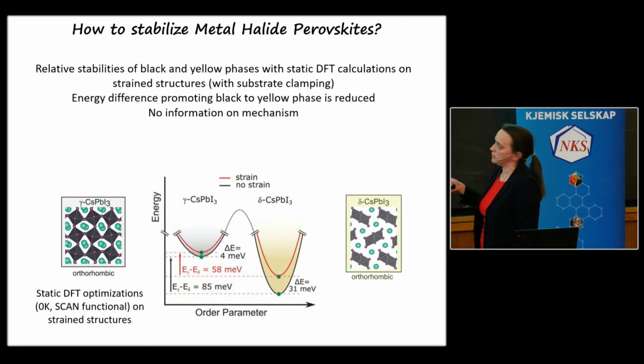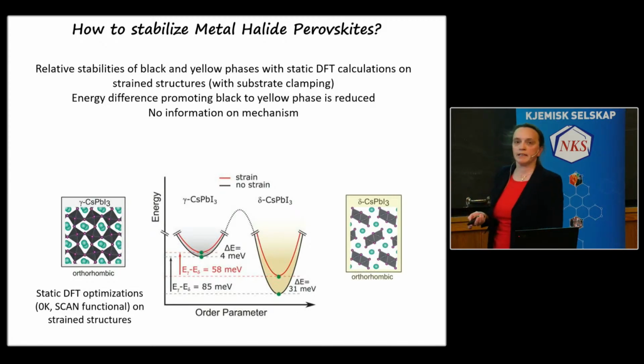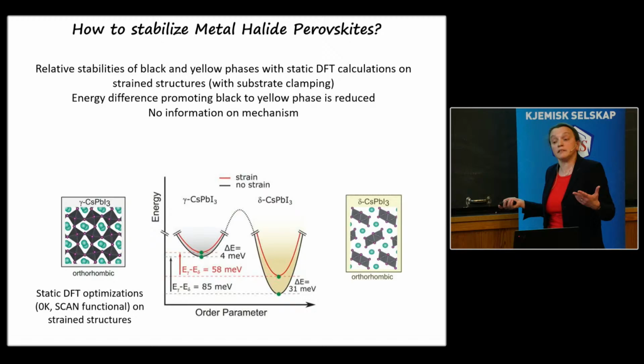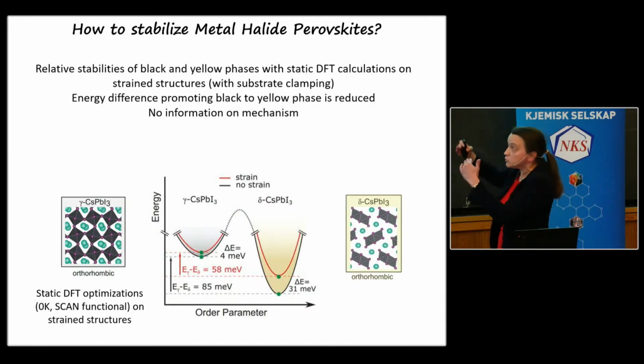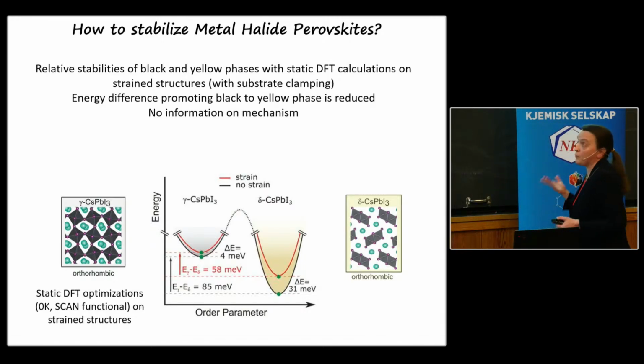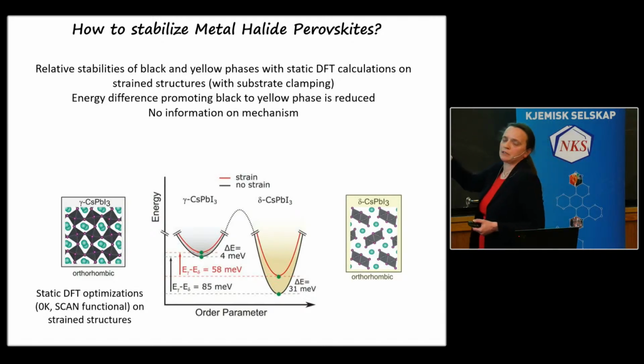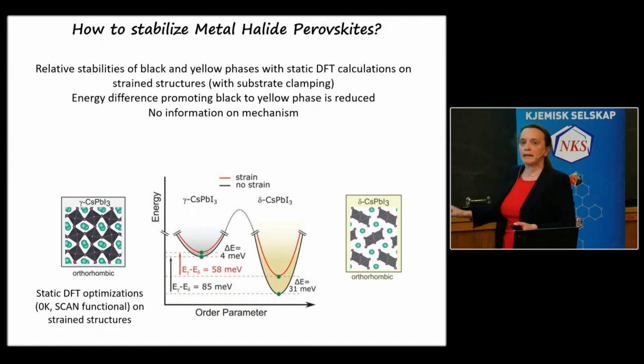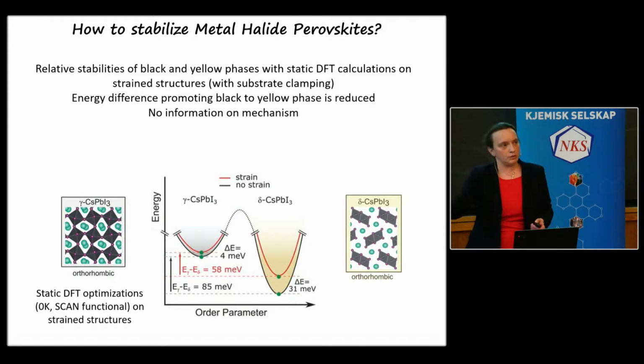The yellow phase, so this phase, is always more stable compared to the phase that we want. But if we induce strain, and these are calculated profiles with strain, we can see that we can modulate this difference and make this difference between these two phases more favorable for the applications. This is only part of the explanation, because this does not say us anything about the mechanism that leads us from one phase to the other.